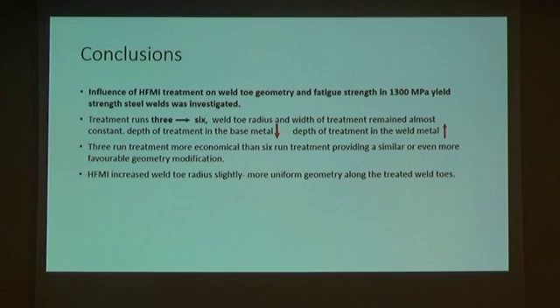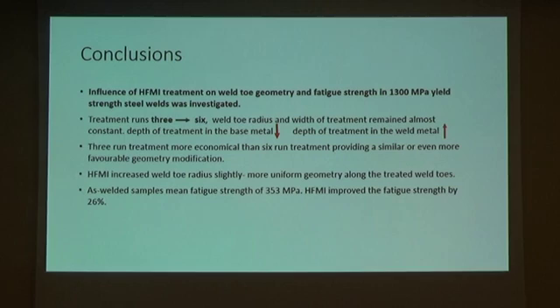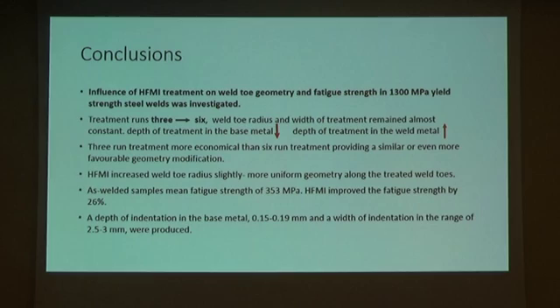HFMI increased weld toe radius slightly but resulted in a more uniform geometry along the treated weld. The treated samples showed a high mean fatigue strength of 353 megapascal, and HFMI increased the mean fatigue strength by 26%. Depths of indentation in the base metal of 0.15 to 0.19 mm were measured, and a width of indentation in the range of 2.5 to 3 mm was produced.